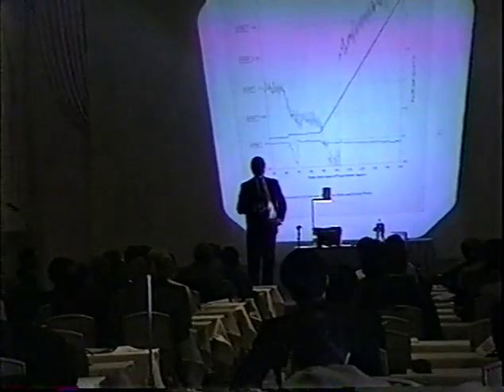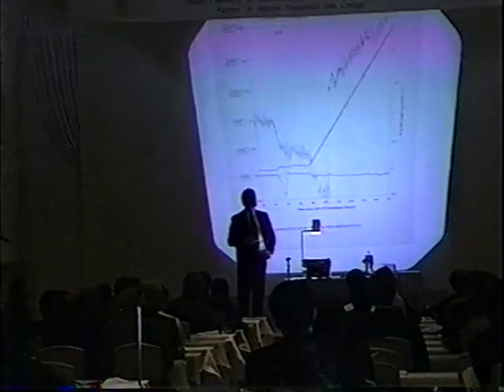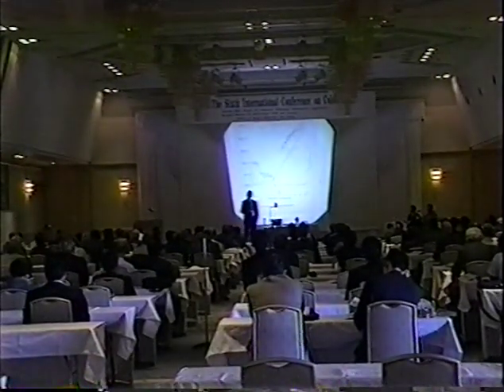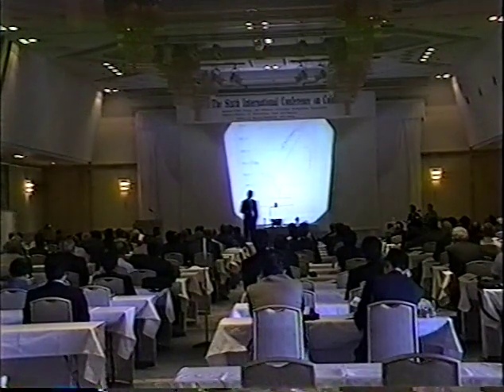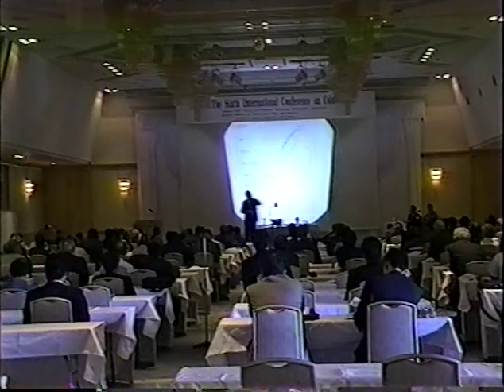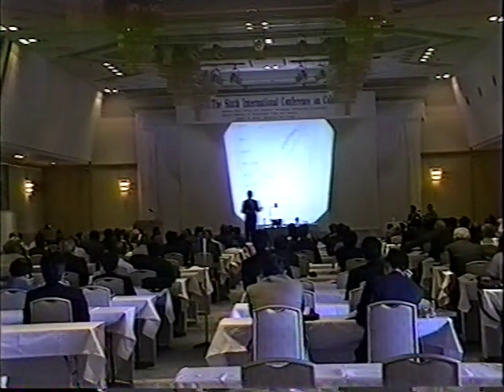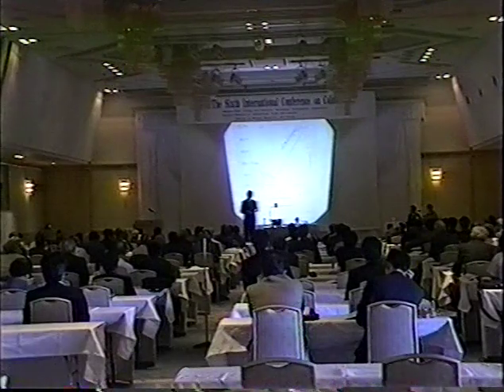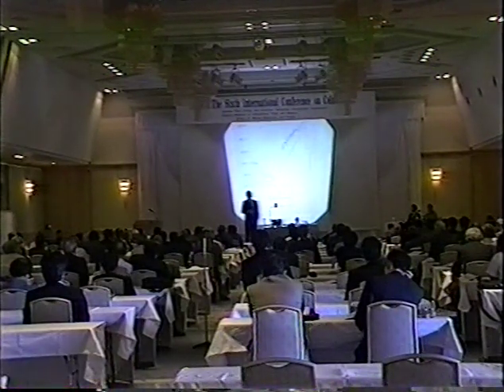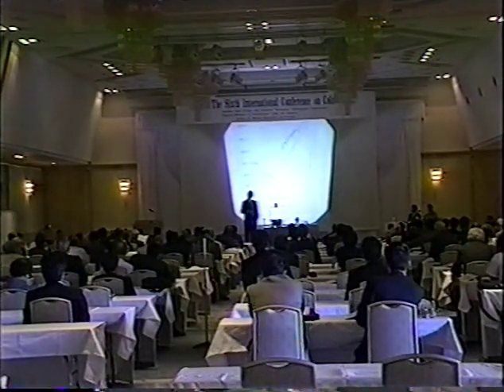So you don't see any real difference between the 1 millimeter diameter and 3? There is a difference, and a real difference. What's the difference? The difference is swamped by the differences in the variability of the metal supplies. But the first, most successful series of experiments that we performed was with a 1/8 inch wire obtained from Engelhard, which we machined down to 3 millimeters. And we stuck with 3 millimeters for a very long time. Latterly, we have used 1 millimeter wires because they load more quickly, but we haven't really been quite as successful with 1 millimeter. But the statistics on that are quite poor.